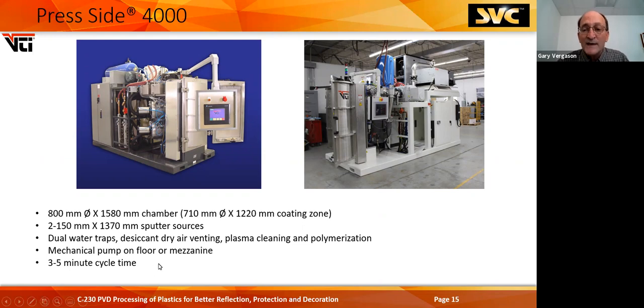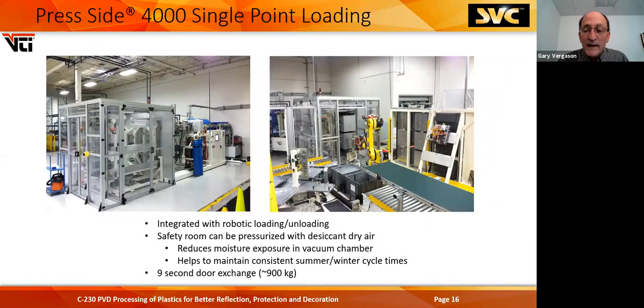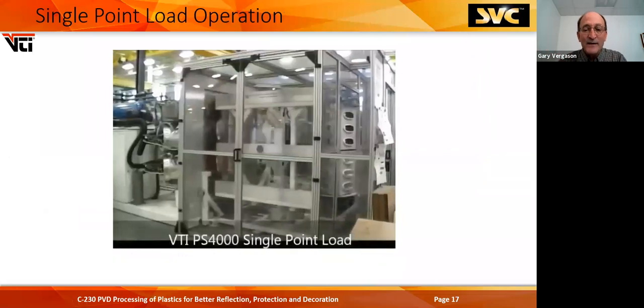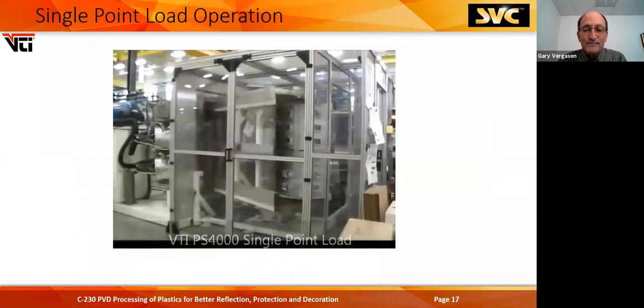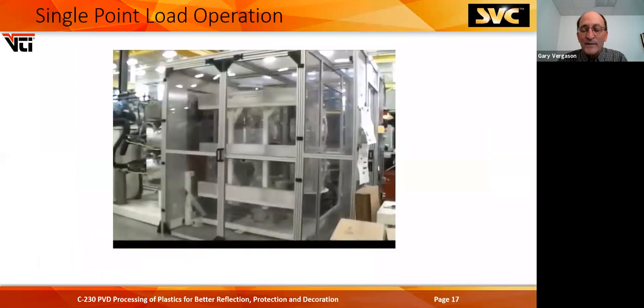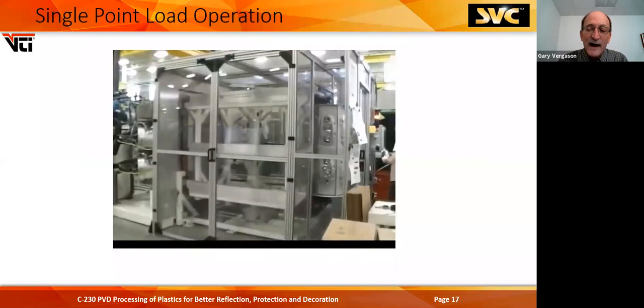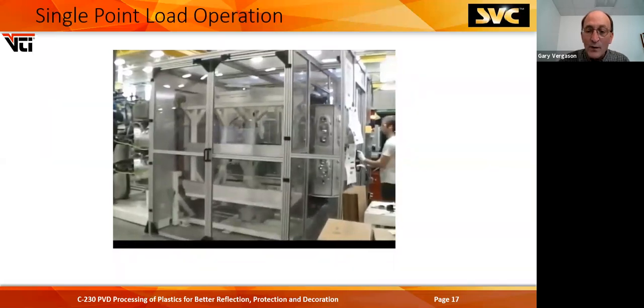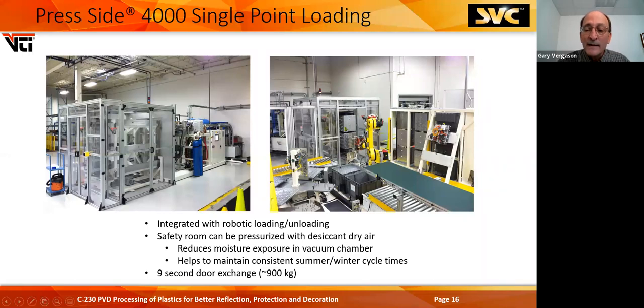So two large plastic injection molding presses can feed one of these machines. We've added the single point loading in here. One customer had a little bit of issues with their staff. So they ordered the single point load where the doors come together, spin around, and then presents the coated parts to the operator. So you could either have an operator load and unload these, or like in the previous slide, a robot can come in here and pick these up and set them down. So they had probably at least three robots in this cell. And it was really something to watch.